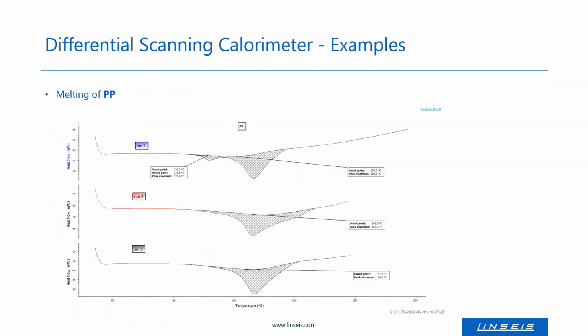And here you see a further example measured by the calorimeter. Here the melting of PP was investigated. PP has a glass transition at really low temperatures, so here only the melting was investigated. In the first run, one sees a clear double peak. After the first heating, the peak changed, so it is only one. This one here is smeared out, so to say, and after the third run, one can also see the melting peak. So this onset point of the melting also changes slightly.